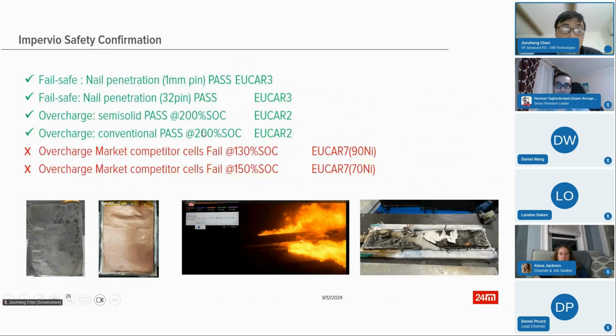Then we do another very aggressive test. Basically, we overcharge the whole cells. When we're doing the overcharge, the lithium will continue to go from the cathode to the anode, and then plate lithium around 100 times more compared to the design. So it will definitely short. You can see this competitor cell, I cannot name it, fail and blow up like hell. Then with this Impervio, there's no internal short from beginning till the end. They pass the test, and then we tear it down. There's no burn, no dendrite growth in the cell.